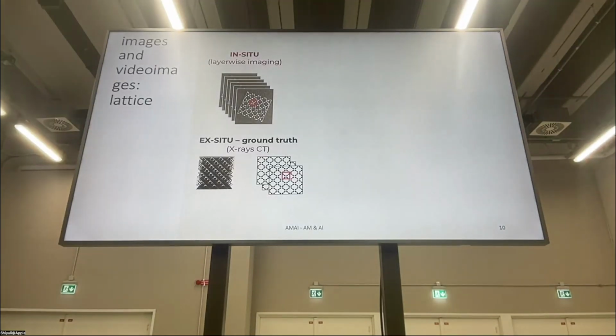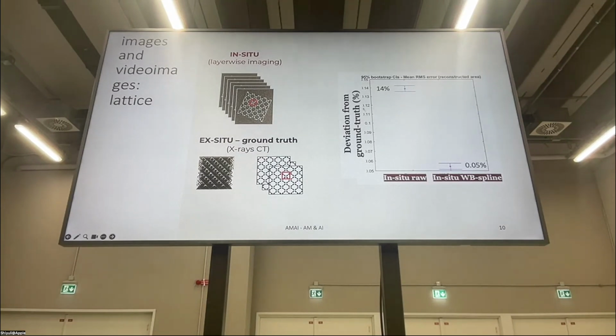The end of the story is that if you're good enough at doing this job in situ and in line, you can be impressively good at detecting the final shape, the final geometry, with respect to what you can do ex situ at the end, which is the ground truth, done by X-ray CT, because X-ray CT is the only way to qualify the part at the end. And this is the final performance of how good we are at detecting the shape of the lattice structure at each layer with respect to the reality measured ex situ via X-ray CT. With our weighted B-spline solution, we are able to have, in situ and in line, a deviation from the real measurement done ex situ which is quite negligible. It's 0.05%.